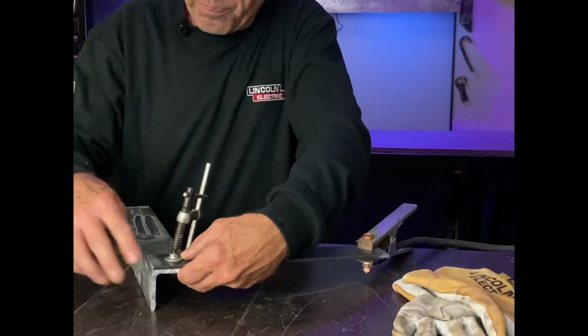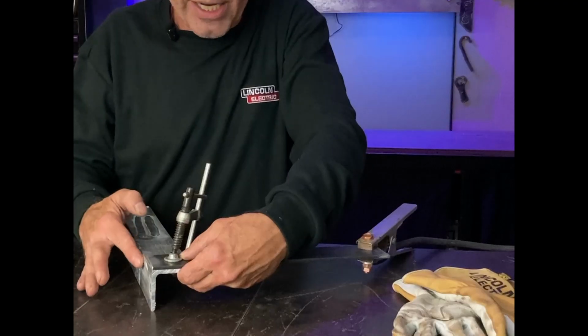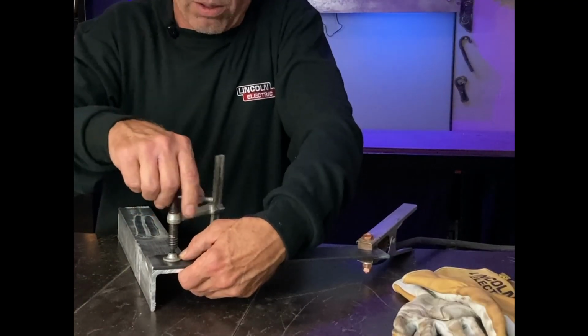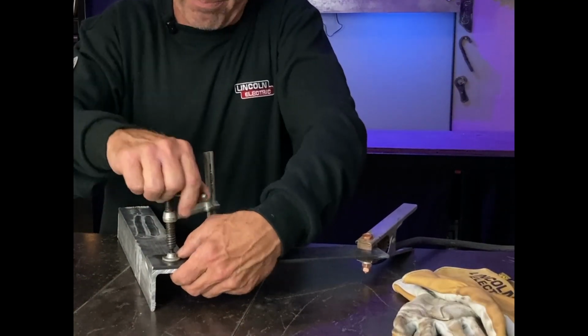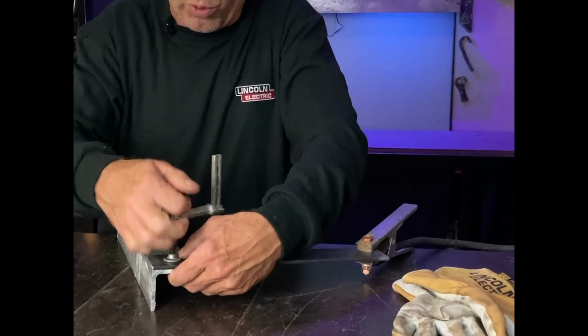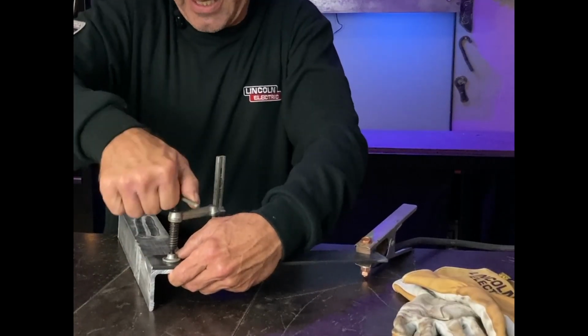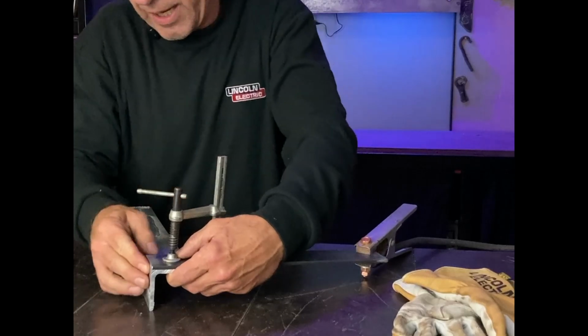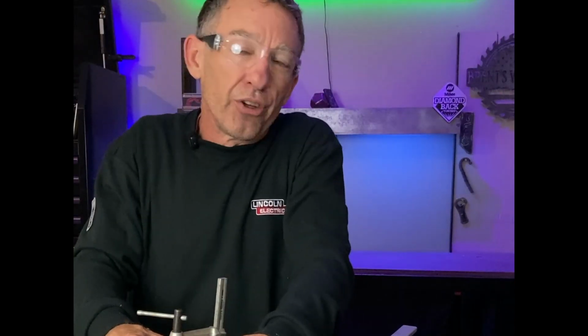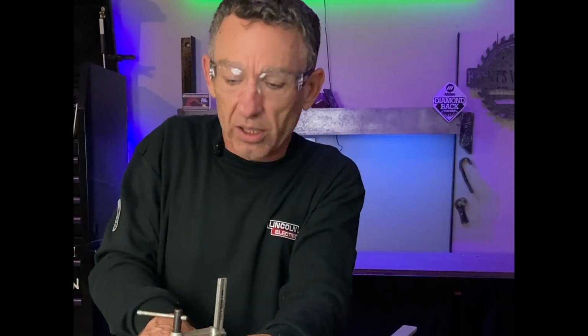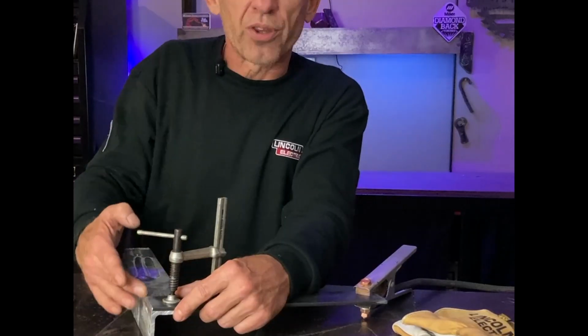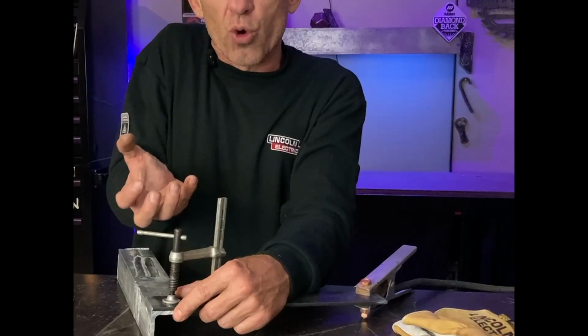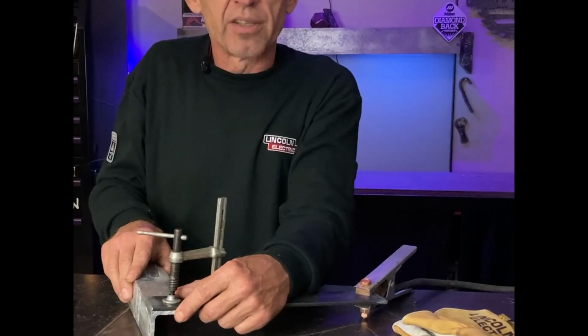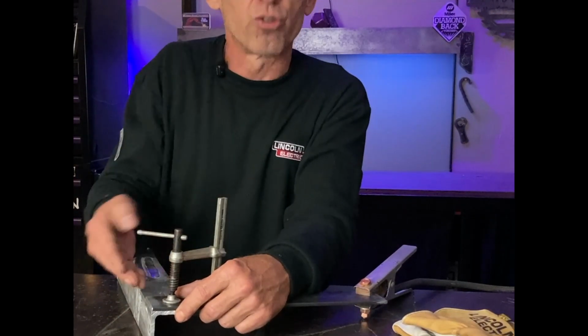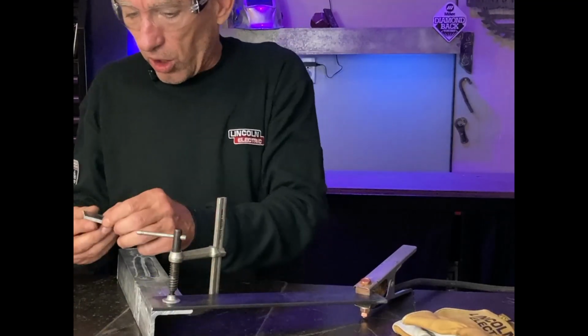Some angle iron or angle material will have a slightly radius edge, and that can be a benefit as well, because it's going to give us a little gap behind the root. So if we're getting full penetration on the joint, it gives you somewhere for that weld to go, right? And by putting a backer on there, we're also using a form of shielding, because we're not allowing any air to get to the backside of the weld, which is going to make it look kind of nasty. So in this case, with having that backing bar, it's going to hold the argon in the joint, and we're not going to have that same level of contamination that we would get if we were trying to just do this open.